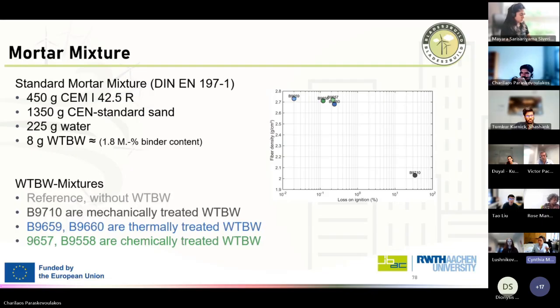Just to keep it simple, we also did concrete tests, but I think this is something where we can compare our results from adding these wind turbine blade waste with other supplementary cementitious materials and stuff like that. So we added 8 grams of fiber per mixture, which is more or less 1.8 mass percent based on the binder content to our mixture.